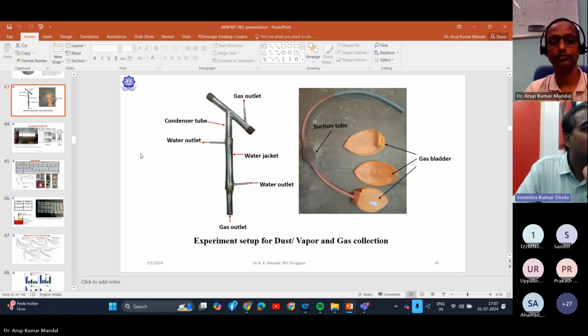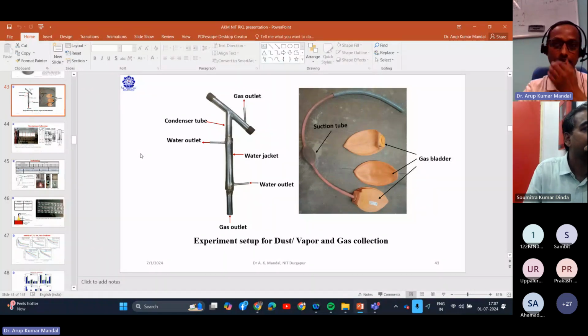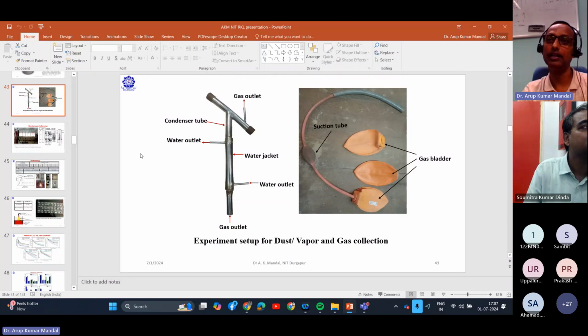But how deep, and beyond that what happens? Actually, you cannot measure this at high temperature. We can calculate it from the liquid metal density, and if you calculate the velocity of the gas, then we can calculate the impingement velocity or the profile which is created, like the crater diameter. We can measure it. Do you use a stirrer in the molten material? No, there is no provision for stirring.